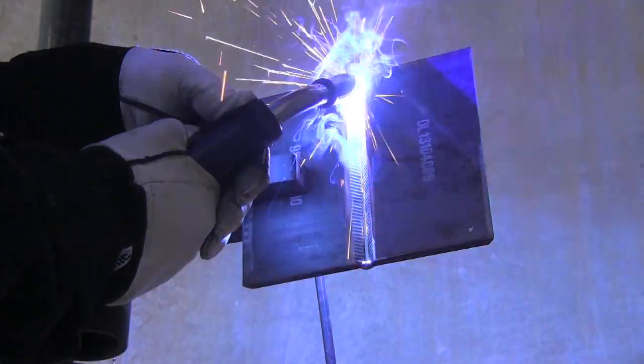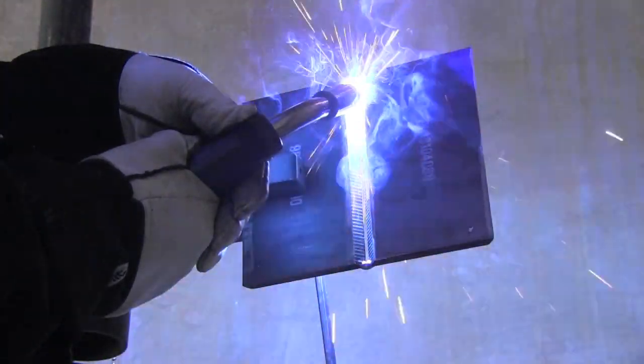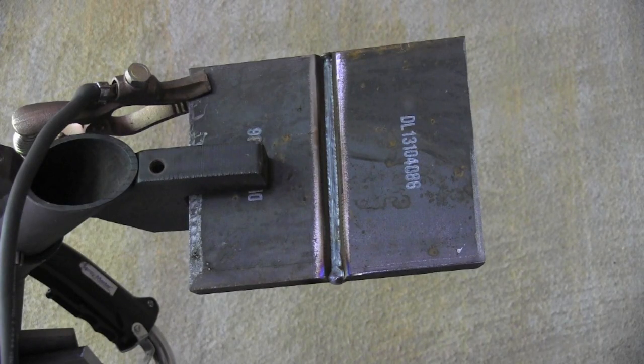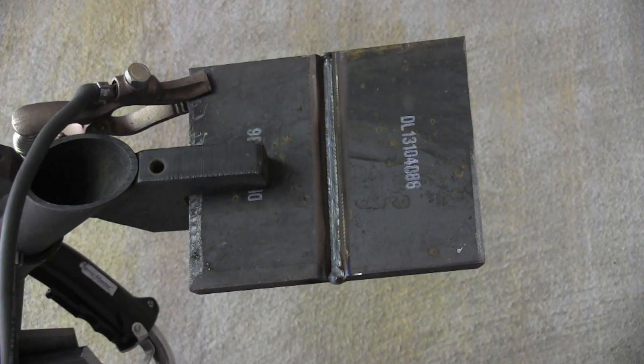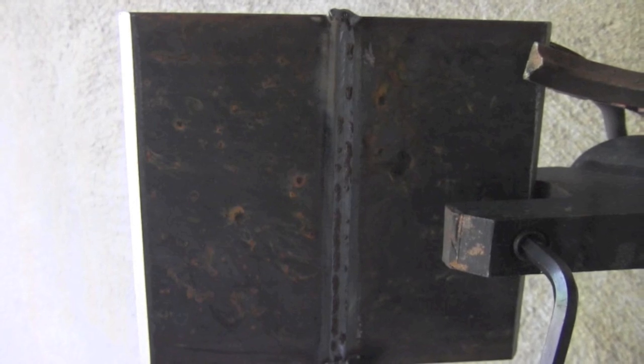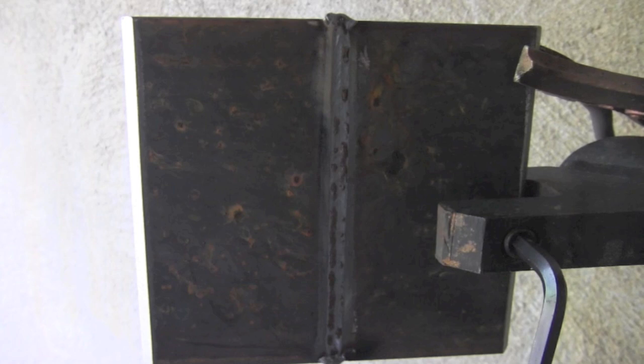Now, this is a perfect scenario where you might be successful going downhill MIG. Clean, bright metal, no mill scale to weld over, and a gap and a nice open groove. The bevels on this plate are 37.5 degrees, which means it's primarily used for practice for pipe. But a lot of pipe root joints are put in just like this, and it works really, really well. It's really hard not to get 100% penetration through the back side, and you can adjust that with your wire feed speed if you want it to poke through a little bit more.